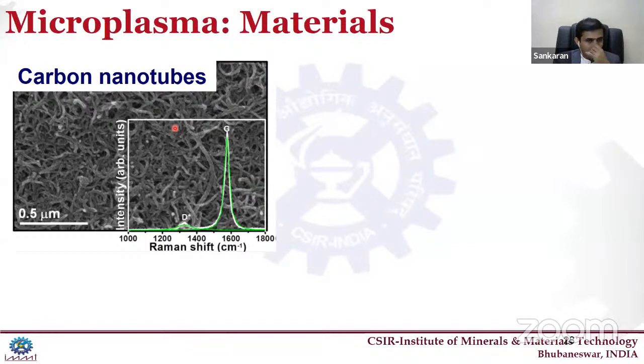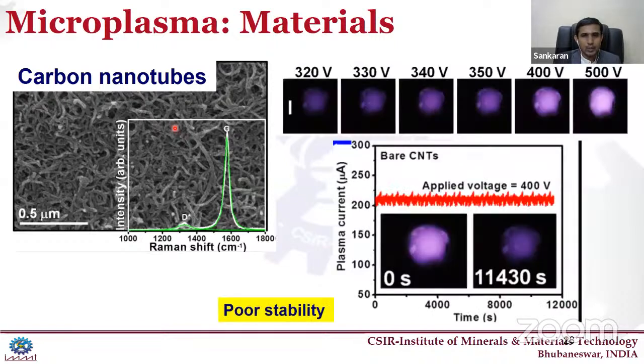So we have also tried to use this microplasma based carbon nanotubes as a cathode device. But the major problem we observed with these microplasma based carbon nanotube devices is that the carbon nanotube is a good primary electron material, but it cannot withstand the plasma for a longer time. So the uniformity of the plasma emission is very poor. It can emit with low applied voltage, but the plasma is not very uniform.